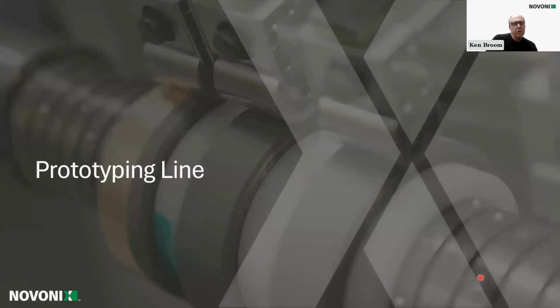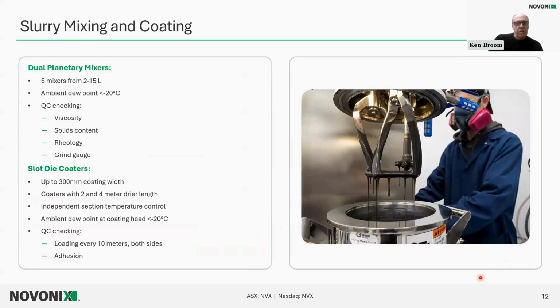So I was going to go into some detail on our prototyping line next. For slurry mixing and coating, we use dual planetary mixers for slurry mixing. We have two 2-liter mixers, two 5-liter mixers, and a 15-liter mixer. The atmosphere in our mixing room, the dew point is lower than -20, typically lower than -25.